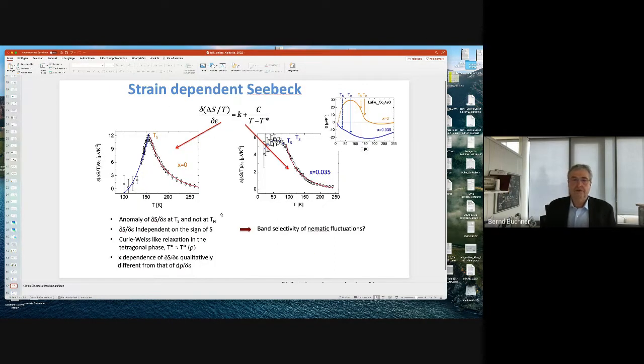If you now plot these changes, these strain dependencies, they do not show a sign change. So in both cases, they are positive. So that already highlights that probably these nematic fluctuations, this nematic susceptibility, are band selective. So holes and electrons react differently to the strain. So this is a question to theory. And we also see that for the parent compound, this change is much larger than for the doped compound, and that's quite different from what we have in the resistivity.